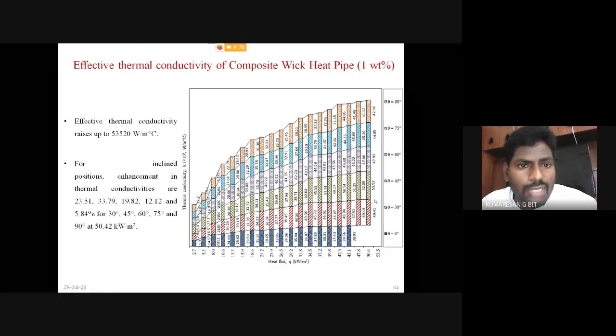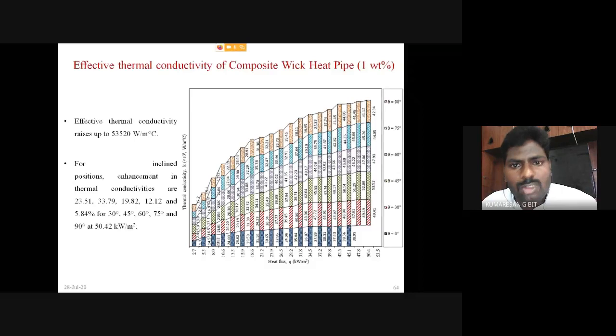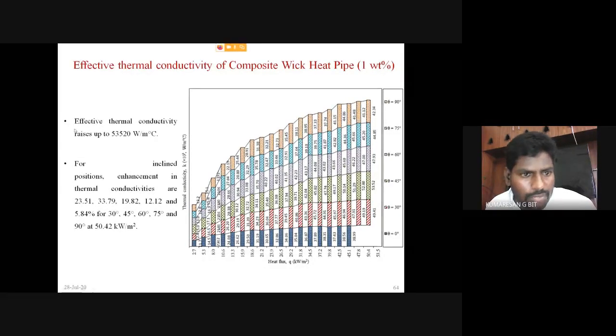Then next, effective thermal conductivity comparison of composite wick heat pipes. The effective thermal conductivity of the heat pipe rises up to 53,520 watt per meter degree Celsius for the heat pipe operating with a combined sintered and mesh wick at 1 weight percentage and 45 degree inclination angle.